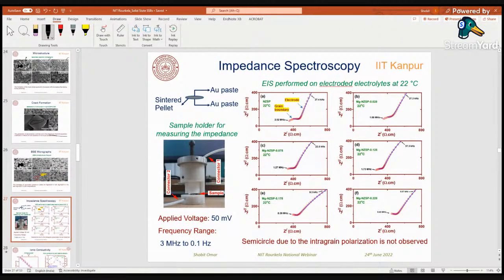We did impedance spectroscopy to understand the conductivity of these solid electrolytes. This is our room temperature sample holder, and we place our sample here, with an upper piston and a bottom piston, and we place our electroded sample and do the impedance spectroscopy. Of course, at room temperature, we are not able to observe the grain semicircle, but we have observed a partial grain boundary semicircle, and from there we are able to get the total ionic conductivity of this material. This was done at room temperature, but we also did it at 0 degree centigrade as well.